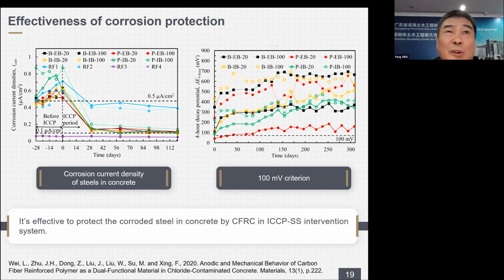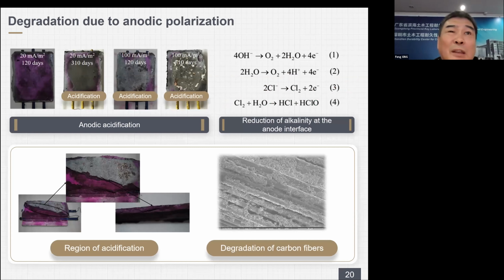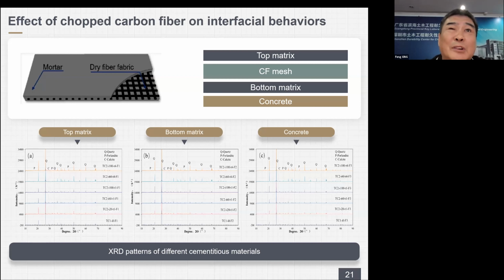As you can see, the steel corrosion was successfully prevented. It should be noted that during the long-term service of the CP, anode degradation and interface acidification are unavoidable. Chopped carbon fibers and other conductive materials were incorporated into the cementitious matrix to form conductive mortar, forming a three-dimensional conductive network with a primary anode carbon fiber mesh. The effective anode area was thus increased, and the concentration of hydroxide ions in the interface region was reduced accordingly.